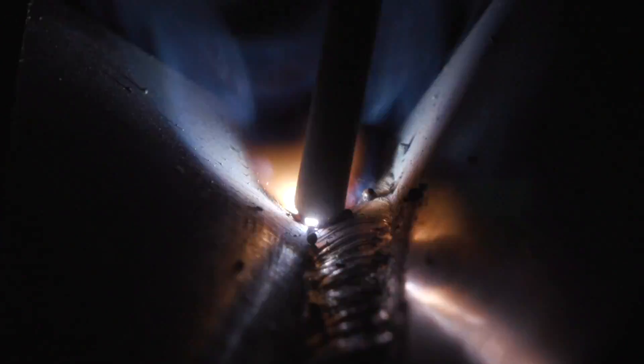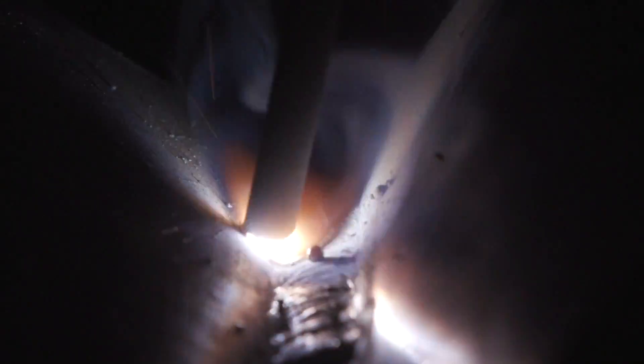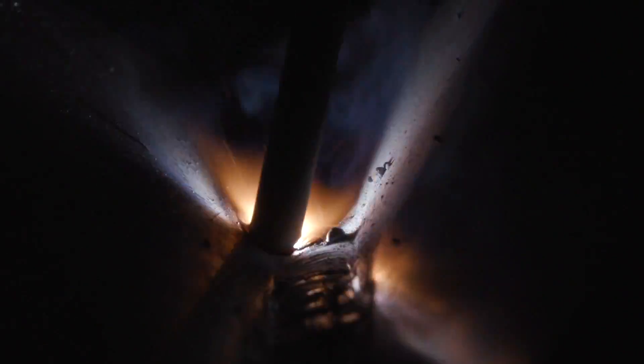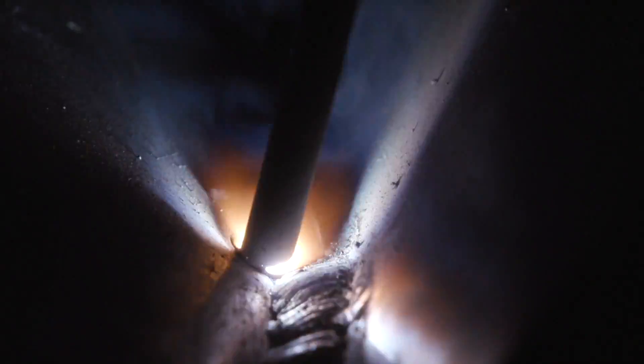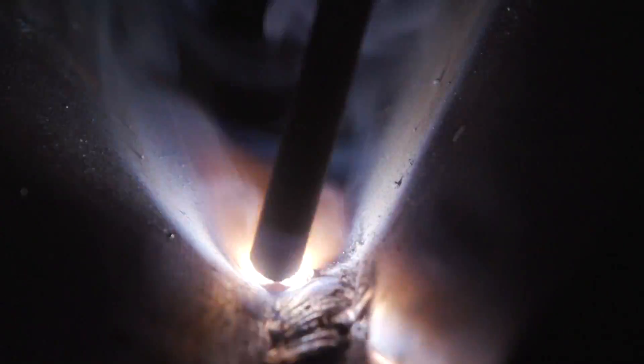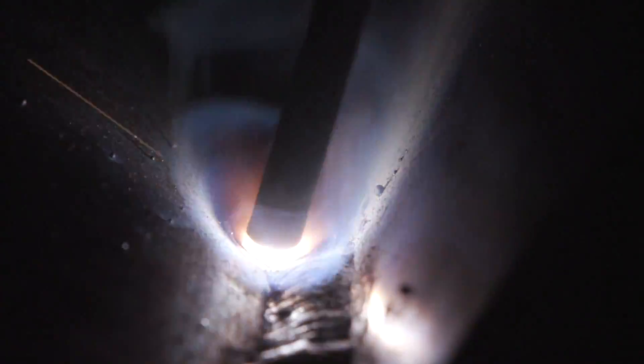Notice my work angle is favoring that stainless steel side a little bit more. I'm just going to go down the toe of that previous weld, the toe where it connects on the stainless steel side. I want to get 50% coverage, 50% tie into the stainless, 50% tie into that previous weld, because pass number three that I put in from the carbon side should cover up this pass number two about 50% as well.